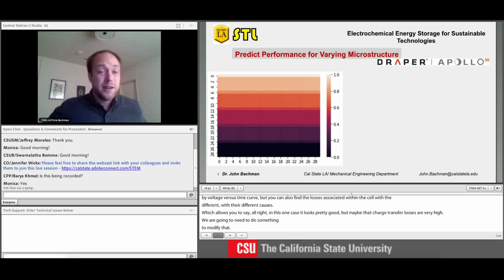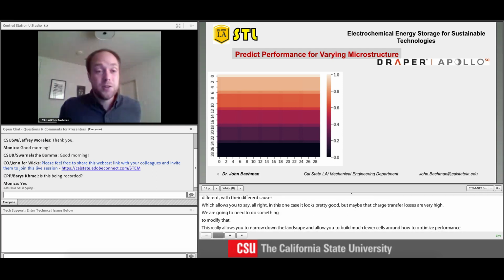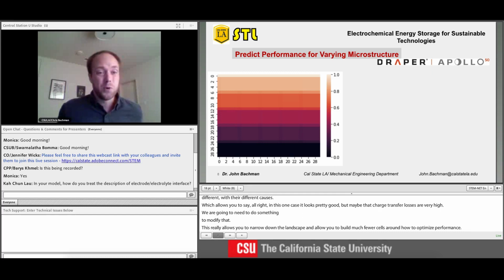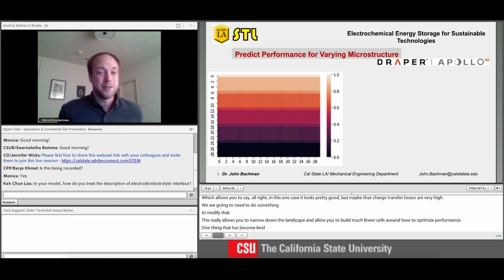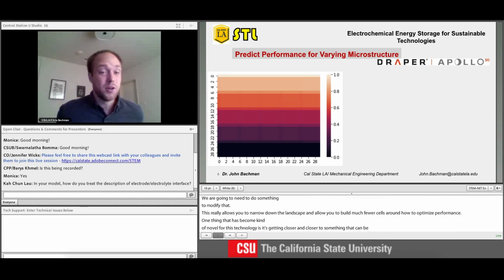And one thing that has become apparent now that this technology is getting closer and closer to something that could be commercialized is that you start running into more engineering problems associated with just making the cells. And so on the left, this is a plot of the voltage in the solid state electrolyte just over a grid. And so you can not only see that there's a gradient up and down, but there's a slight mesh behind it.